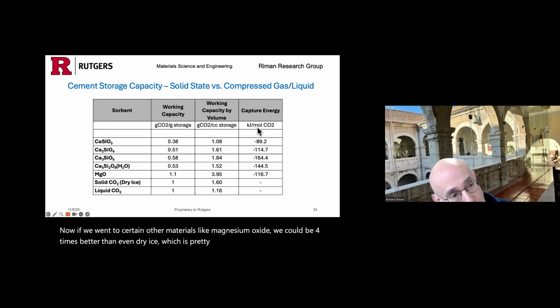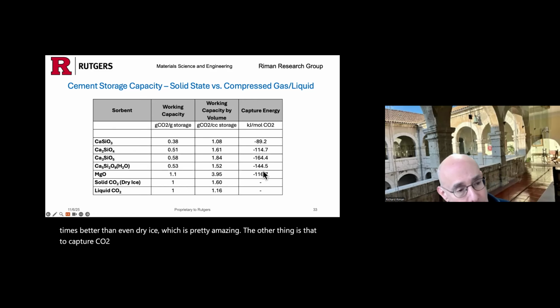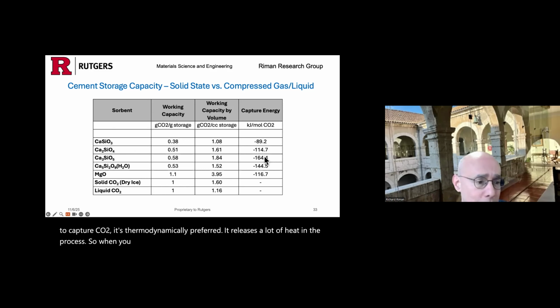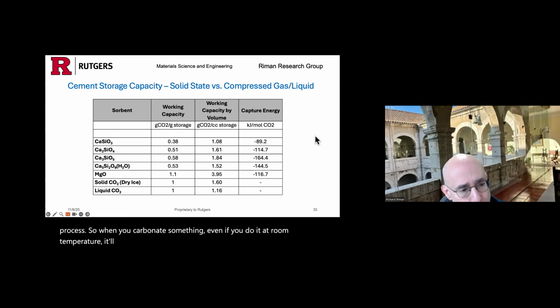The other thing is that to capture CO2, it's thermodynamically preferred. It releases a lot of heat in the process. So when you carbonate something, even if you do it at room temperature, it'll heat up to about 40 degrees C. So there's a lot of energy that's stored. And these materials are very sensitive to CO2. So you can pick up CO2 directly from the air or directly from water, as well as flue gas.